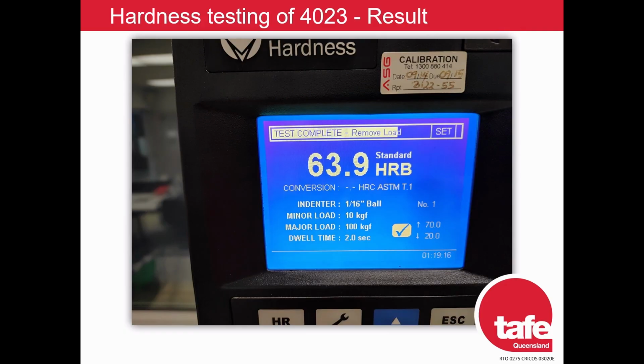The result is 63.9 on the Rockwell B scale, confirming that the 4023 is significantly softer than the TOH and the 4140. This correlates with its lower carbon content and its inability to form martensite under the same quenching conditions.